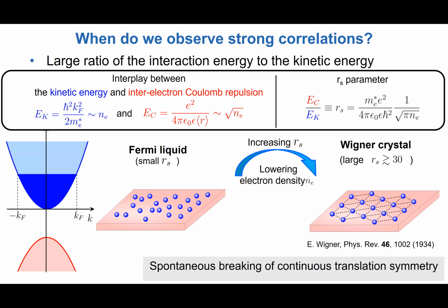Okay. If we can increase RS, for example, by lowering the electron density without going into this disorder limitation, then it was predicted almost 90 years ago by Eugene Wigner that the electrons would actually spontaneously break translation symmetry and form the so-called Wigner crystal. Okay? And this requires that the RS parameter is larger than 30, according to quantum Monte Carlo calculations.